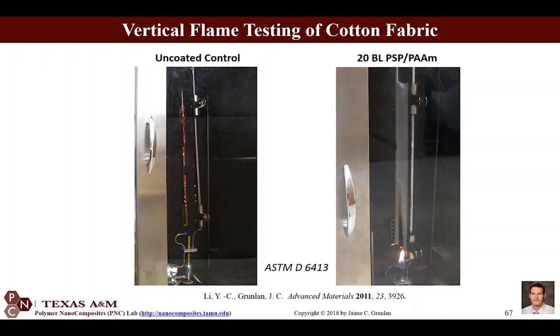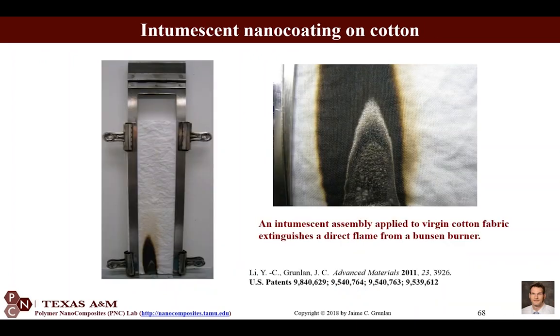And then this coated fabric passes the standard fire test, which is this ASTM 6413. It's a vertical burn test. And you can even, with your naked eye, see kind of this micro intumescent effect. So we're getting what you get on the steel girder in a skyscraper, just on a very micro scale.